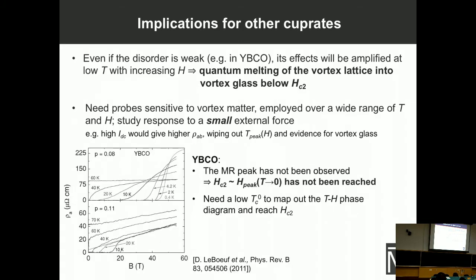And as far as magnetoresistance goes, as I said, they observed only positive magnetoresistance. So these are a couple of examples. In other words, the peak has not been reached, although here at low temperatures you can see something that could become a peak. So what would be needed, I think, is to perform a similar study on YBCO with a relatively low TC, so one can hope to reach this regime, the upper critical field, basically, and see how the results compare to these results on cuprates.